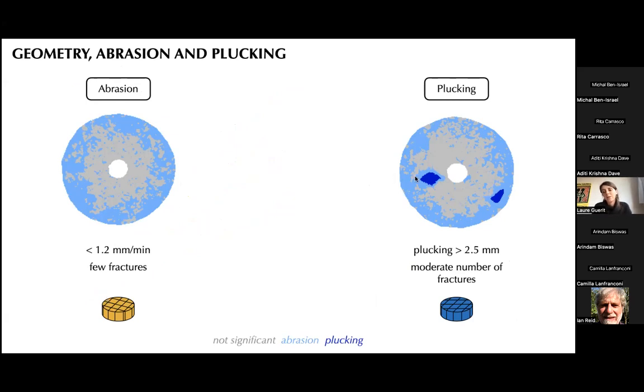On the other side, we have experiments with plucking. Plucking is always quite intense, as we have rates of more than 2 millimeters at once. I did not mention it, but the discs are 2 centimeters thick. So it's about 10% of the thickness that is removed at once. And these experiments are the ones with a moderate number of fractures.